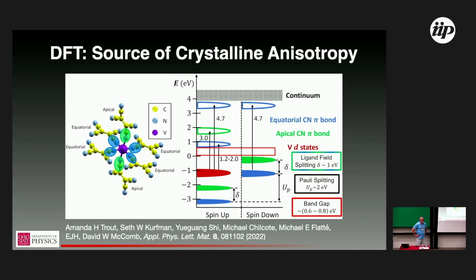But if it's amorphous, I think it's amorphous in the sense of amorphous silicon, which does still have a local crystal structure, so you can verify that. And certainly the calculations bear that out, right? That's the energy structure that we see. It's a bit challenging to get structural information out of the system for a couple of technical reasons, but we're quite confident of the local coordination.